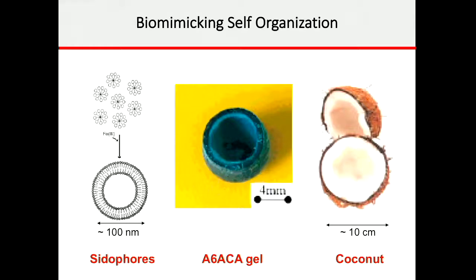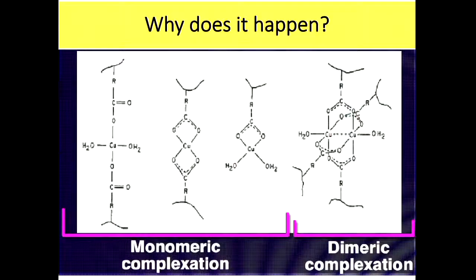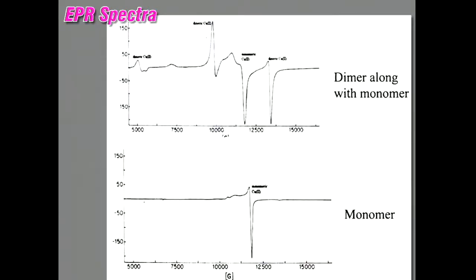Now there's a mechanism there, because the cupric ion basically comes in. When we did the analysis, we found there are two species, the monomeric as well as dimeric. The statistical probability of two cupric ions coming together makes a dimer. And these dimers are tightly squeezed, so to say. So now you can imagine the diffusion process, tight squeezing, and then creating a rupture. And that is what, of course, we verified by taking the EPR spectra on the presence of both of these.